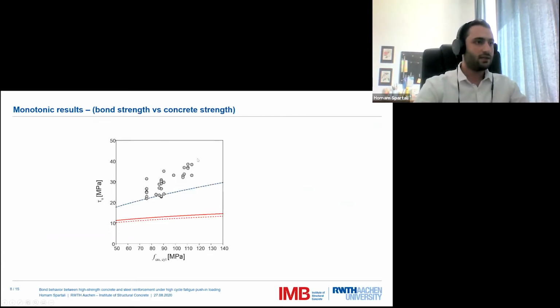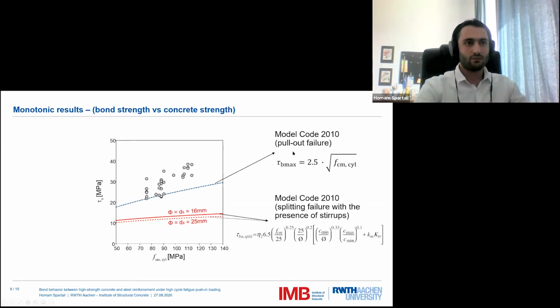Now in this figure, we see the bond strength obtained from each one of the monotonic tests plotted against the concrete strength that we obtained from the accompanying material tests. Let's compare our results with the formulas that are available in the model code. In the model code, it's distinguished between two kinds of failure: the pull-out failure, which is given by this equation, and the splitting failure with or without stirrups. In our case, with stirrups, which is represented in this equation and these two curves.